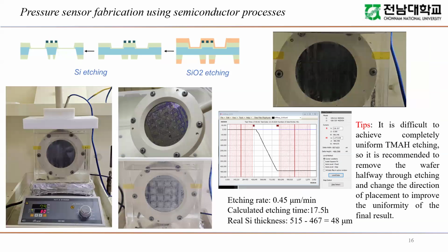Then we do the TMAH etching for the backside. Since the etching rate was 0.45 micrometers per minute, we calculated the etching time as 17.5 hours, and the remaining silicon thickness will be 48 micrometers. We discussed that it is difficult to fully achieve uniform TMAH etching, so it is recommended to remove the wafer halfway through etching and change the direction of placement to improve the uniformity of the final result. So this is the final result of our fabrication process.